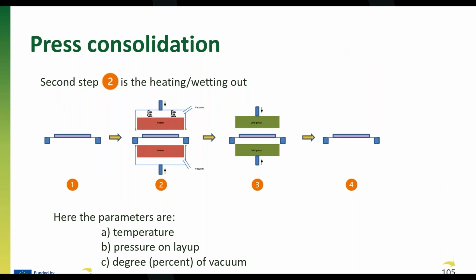The second one, you actually go into the heating. We have a separate heating system here because we have the temperatures that you can control at a steady state. The pressure you can put on the laminate for the impregnation, and also you can have vacuum put on if you have a very sensitive system here. So you can also decide which percent of vacuum you are going to use. And the reason for having this steady temperature here is that you are only heating the laminate and not heating the mold, or having to cool it down afterwards. Next one, please.